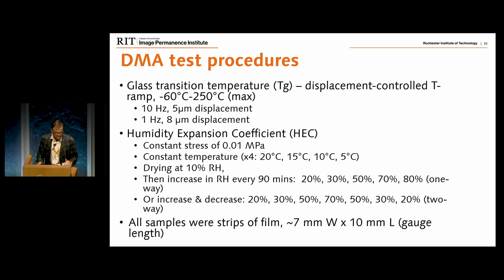And then the sample is being dried at 10% RH and then slowly humidified, allowing for 90 minutes of relaxation at a given RH at each step. And we're doing this either one way in those 5 steps, 20 through 80, or increase and decrease. So we are humidifying and drying the sample without the step of 80%, why I will show you in a second.